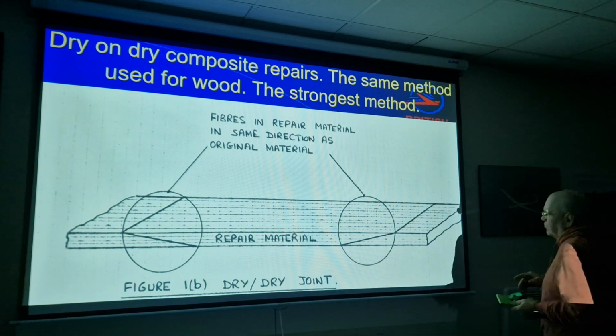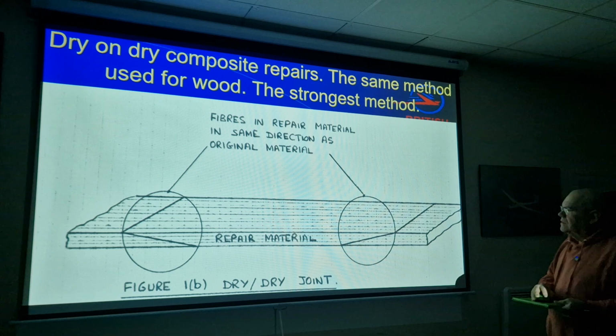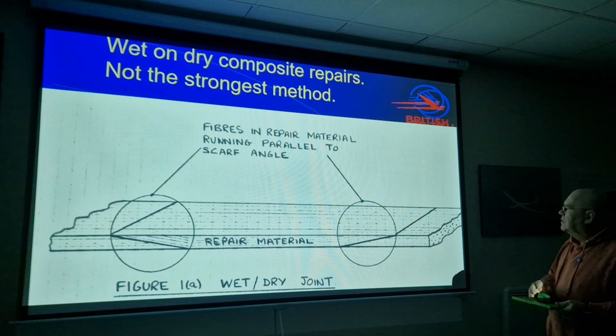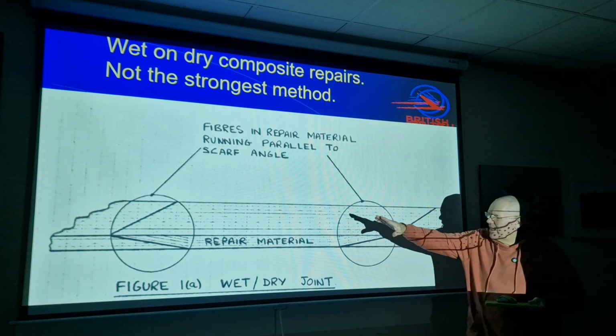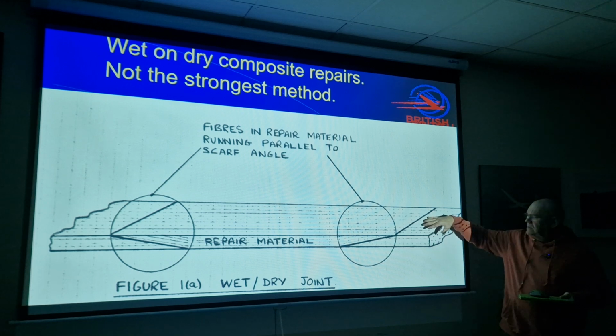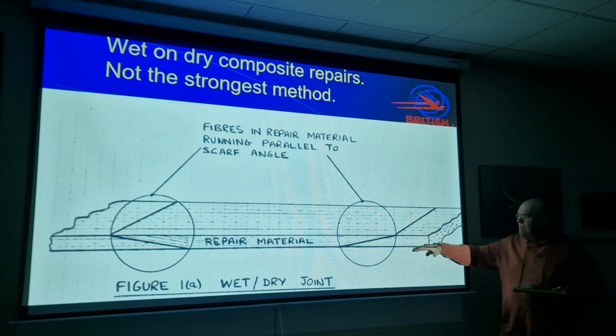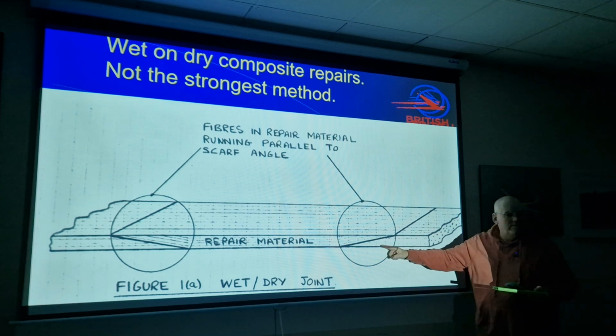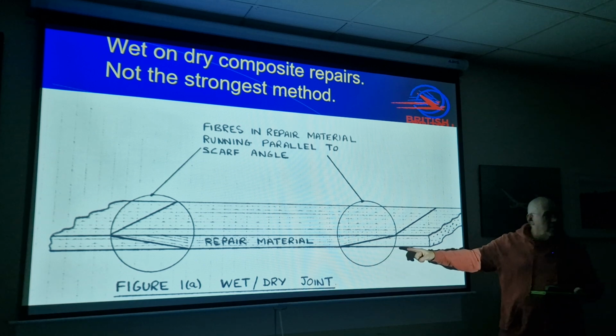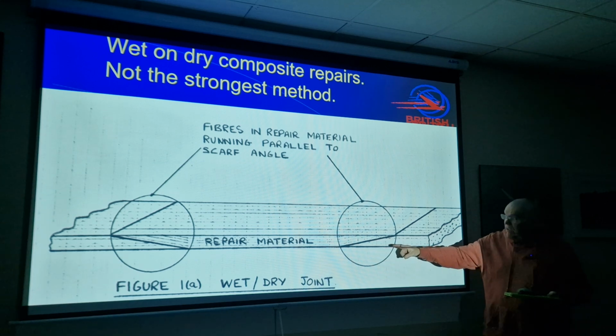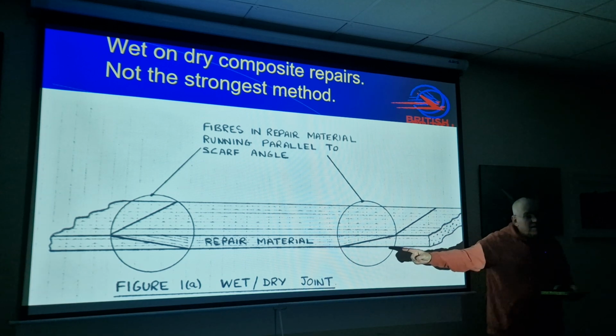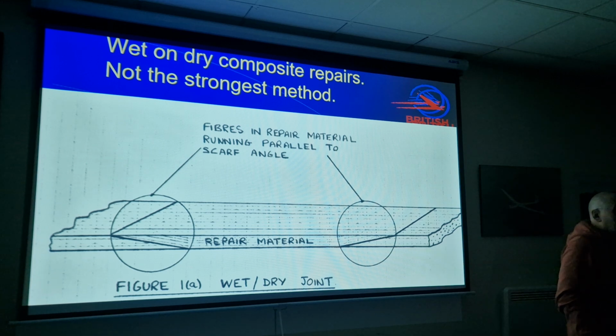Okay. And what they did was, I'll go back to where we were. What they found was, if they just laid more carbon fibre into this and ground it flat, you could never achieve 100% strength. The best you could achieve was about 75% strength. Now, for 30 or 40 years, that's the repair scheme all the manufacturers approved. We did it. None of them have peeled yet.